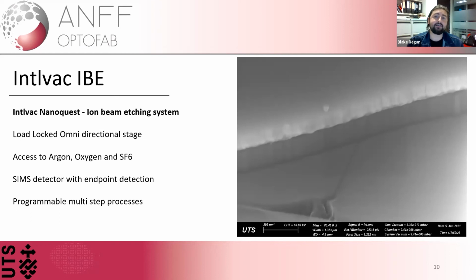But the etch was intended to lower the physical etching parameters while enhancing the chemical etching parameters. So it was a highly active ion with a fairly low acceleration, which basically still achieved some physical etching, which is why you're attributing it to smoothness. So basically the physical etching component would have worn away any resputtered SiO2 from the etching process, but then the oxygen portion of the etch just did most of the work for us. So we had very little wear on our SiO2 mask and a good amount of etching on our diamond. So this was done all on a bulk single crystal diamond that we bought from Element 6.